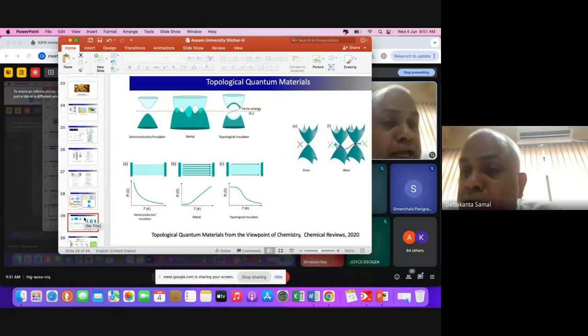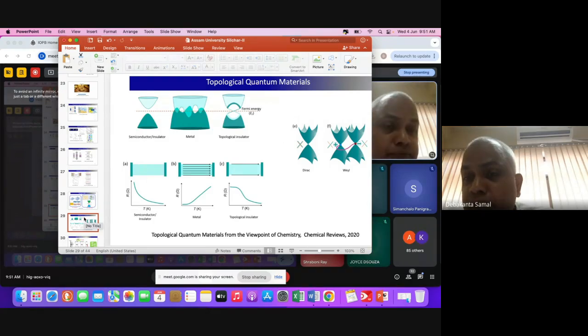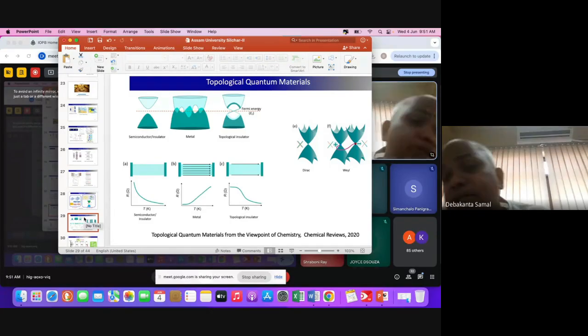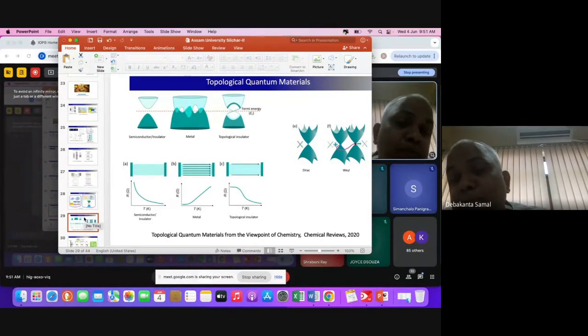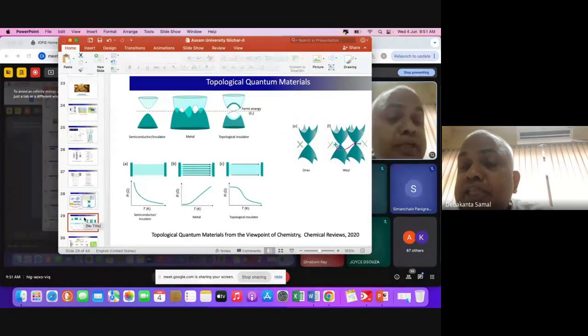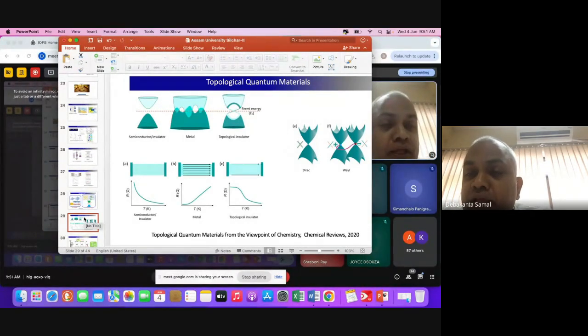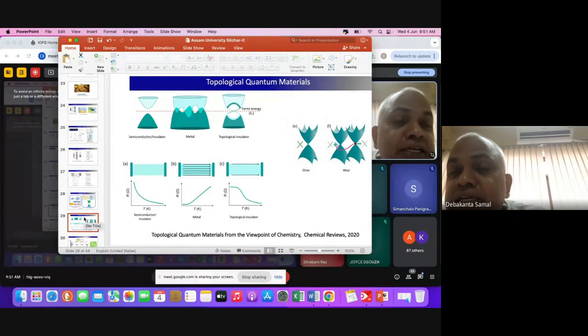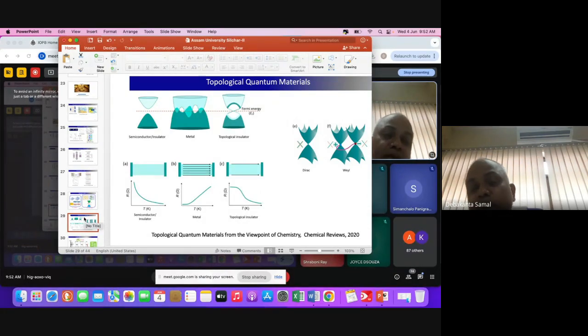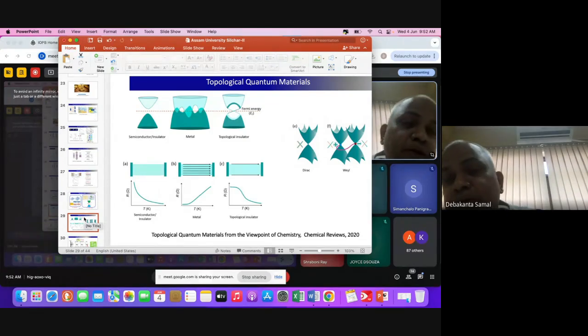You can look at their dispersion by doing experiments like photoelectron spectroscopy, or you can do transport measurements to look at how these electrons, which show a linear dispersion with chirality, for example in a Weyl semimetal, show different transport properties compared to the conventional parabolic electron. That is what we have been doing. I'll not be able to go through it, but we have been using transport properties to distinguish whether it is a Dirac or Weyl semimetal compared to a system where only parabolic bands are there, as in conventional metals.